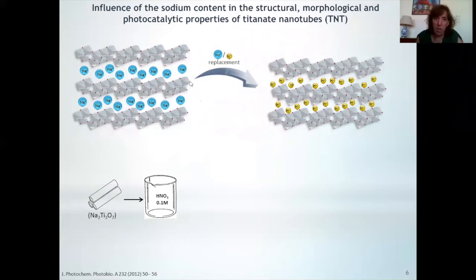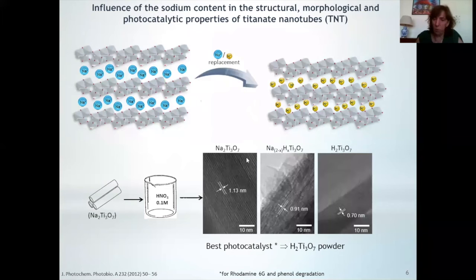As you can see here, the dimension of this interlayer is a kind of shrinking when we change from sodium to H+. And this difference in the material is visible, for instance, in the XRD. It's also possible to see the difference in the interlayers. If we look at the high resolution TEM pictures, you can see that we are reducing the interlayer distance when you change from a solid with only sodium to only H+. All of these are excellent photocatalysts, the protonated powder being the best one.